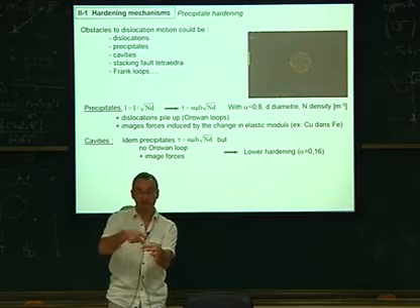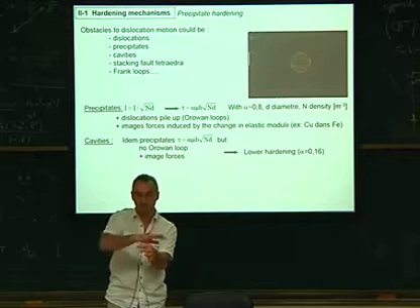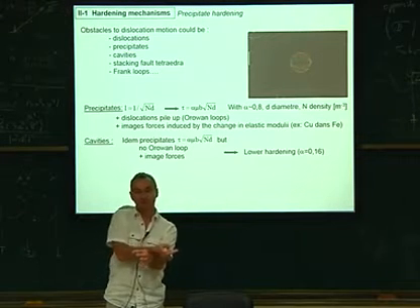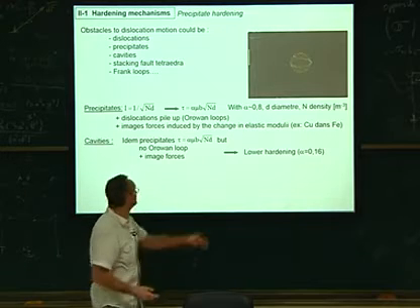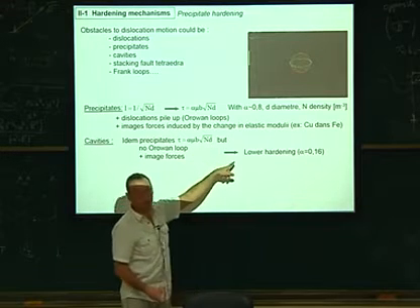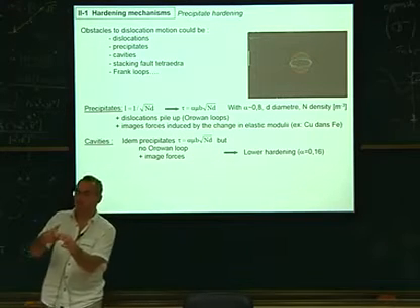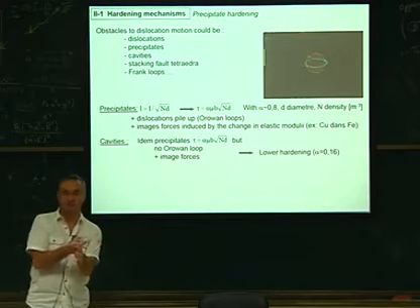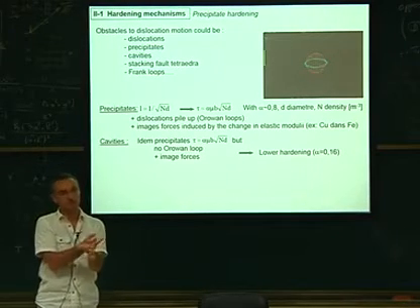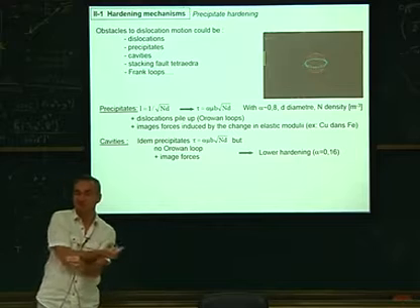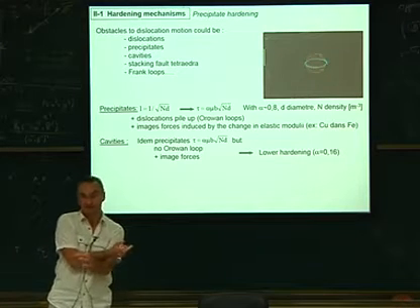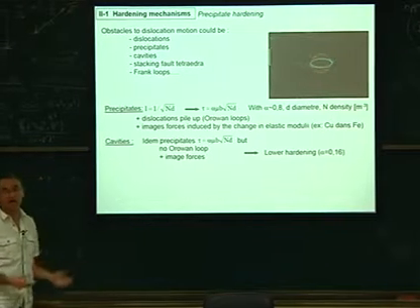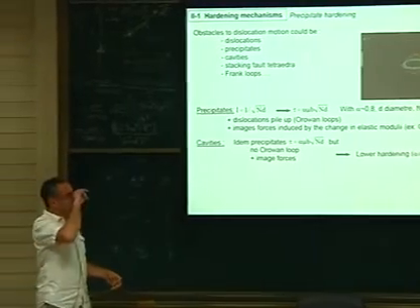You need to create a step on the void, actually, to make the shear step of the void, plus the dislocation length. So this has a small cost, which is 0.16, typically in this factor. So it's not before the void interaction that there is a problem, it's after. To release from the void, it costs some energy, which is because of the shearing process and the dislocation length you need to create again. Okay? So it is indeed a hardening mechanism, the void, but very weak.